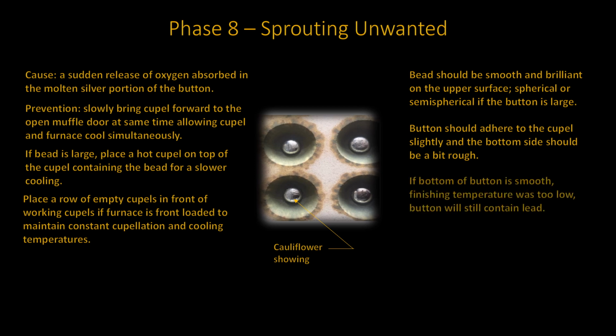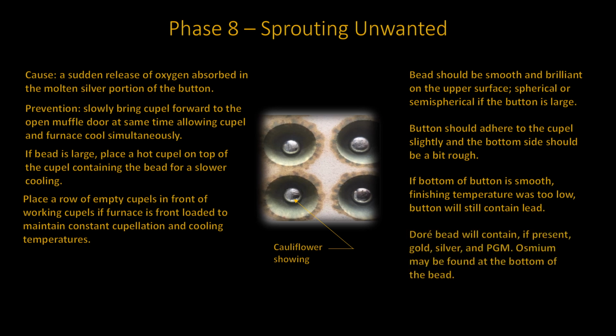If you find that the button is smooth, it will still contain lead. The finishing temperature was too low. In the end, your doré bead will, if any are present, contain all the gold, the silver, and the platinum group metals. Osmium may be found at the bottom of the bead.